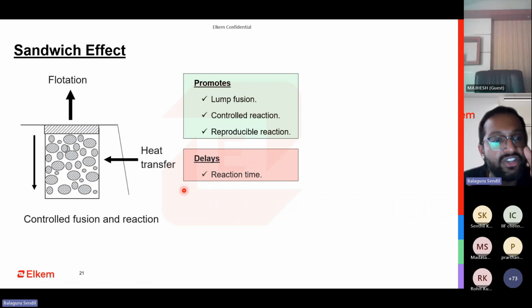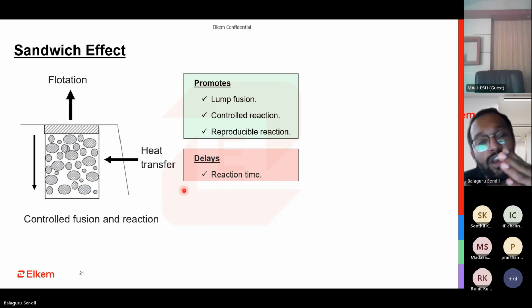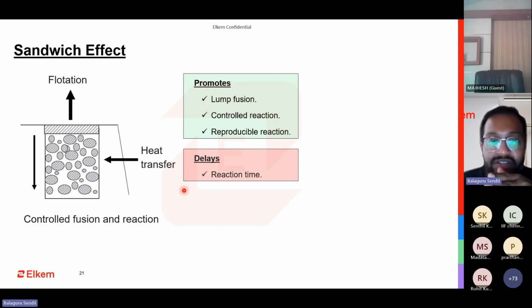So if your magnesium reaction stops before you finish tapping, that means your pocket shape is not correct. The size range of FSM that you're using is not correct. It can be optimized. The reaction should always stop after your tapping ends. That is a very basic thumb rule that can be followed by process engineers on the shop floor. At the same time, if I want to further improve and save cost on my alloy consumption, then I need to make sure that the start of reaction is as late as possible.